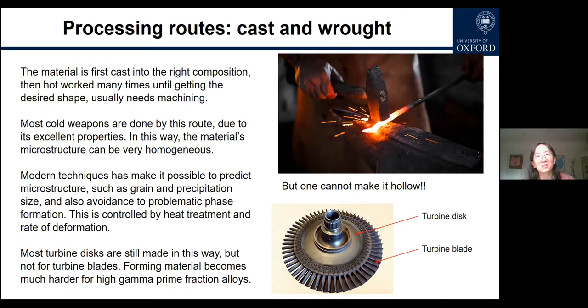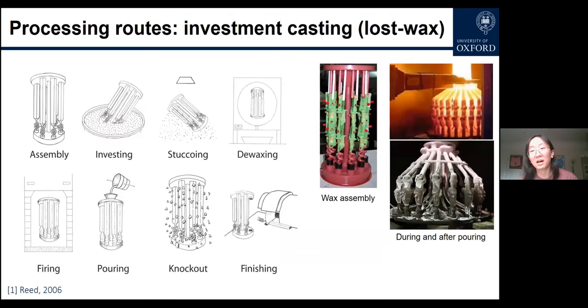However, cast and wrought material can't really be used for all applications. The really big hindering factors are two. One is that it becomes harder and harder to make high gamma prime fraction alloys this way. So these alloys are used for relatively lower temperature but higher strength requirement components such as the turbine disk. The other important reason is that if you go bang, bang, you can never make it hollow, or it's extremely difficult to make a hollow with subsequent machining. That's why we have used cast and wrought materials for turbine disk applications, but not really the turbine blade, which requires higher temperatures.